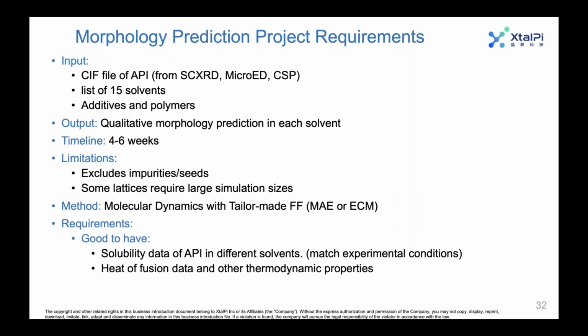So I'm going to conclude the discussion of morphology prediction with some of the project parameters or the project requirements. So the input for this type of model, the thing you absolutely have to have is a crystal structure file. So that can be a CIF file of the API. That can either be obtained through experiments like an SCXRD or microED experiment, or that can even be a CSP predicted structure. Then you need some experimental conditions to simulate. So here I've listed 15 solvent systems, but we could vary that, right? We could look at different supersaturations. These are MD simulations, so you could potentially look at different temperatures, and you can definitely incorporate additives and polymers, as I showed with the last example. So that's definitely an exciting option for this type of project.